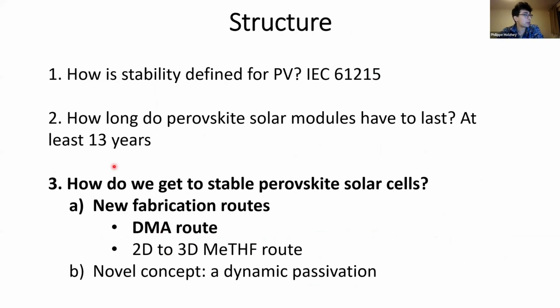So what I will talk about now is how do we get to those stable perovskite solar cells. So we know that we have to get at least 1 order of magnitude higher stability. And I've been working on it for a while. And the thing I can say with certainty is that the one thing which correlates the best with improving stability is changing the way you make your perovskites. So the moment you go away from what has been established over time, this DMSO route, and go to different manufacturing methods, we have been getting a lot better stability data. And so one of those fabrication routes I developed in my PhD was what I call a DMA route.